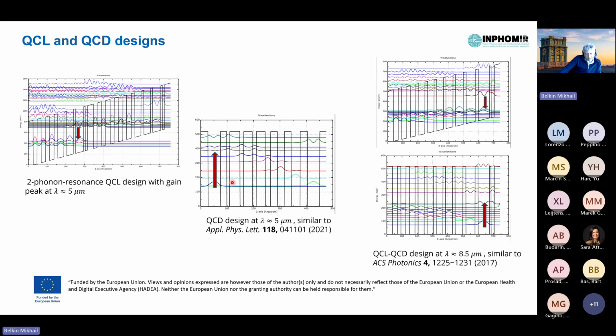For the detector, we used a configuration similar to that reported in the literature, and again adjusted it for our wavelengths a little bit. And for the 8-micron design, actually it is possible to design a quantum cascade active region that is simultaneously working well as a laser under bias and as a detector under zero bias, following this paper. So for the 8-micron peak, we actually don't even need to separately grow another active region on our wafer. The same active region could be used as a laser and a detector.